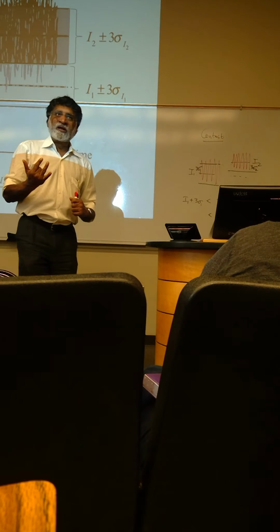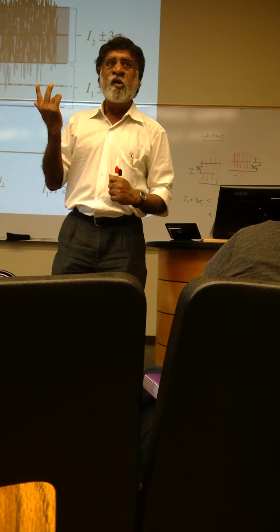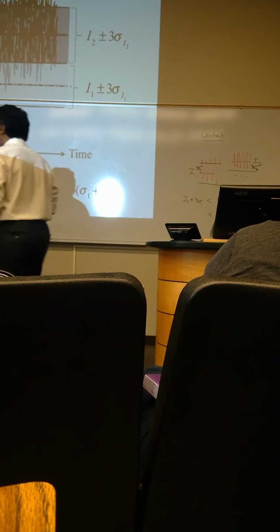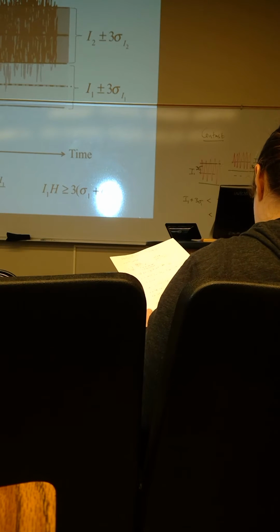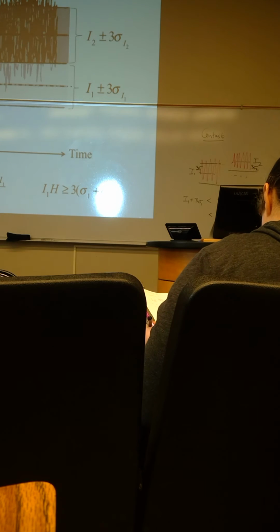And one of the simple things, if you're doing a purely statistical process, is this again a very standard thing. If you have a certain number of counts, sigma is typically the square root of n. So if you have 100 counts, the square root of n is 10.